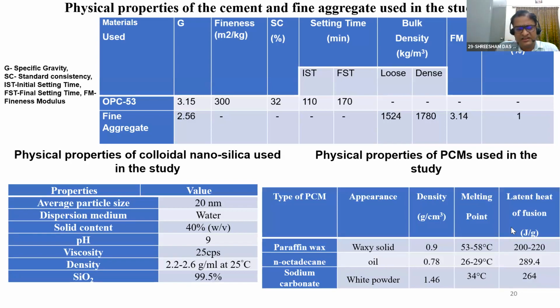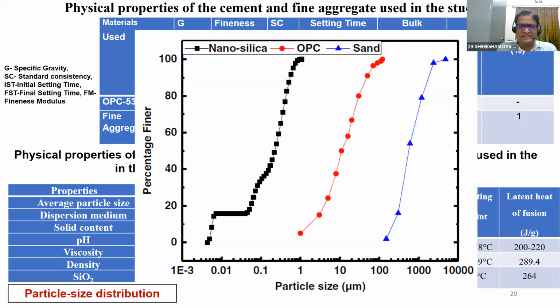So this is the way we've used the cementitious system, and you can see here the nanoparticles. We have used 20 nanometer size particles in a colloidal form, just to avoid any kind of safety hazards. So this is the particle size of the OPC, sand, and nanosilica. My OPC stands in the micrometer zone, my sand lies in the millimeter zone, and nanoparticles lie in the nanometer zone.